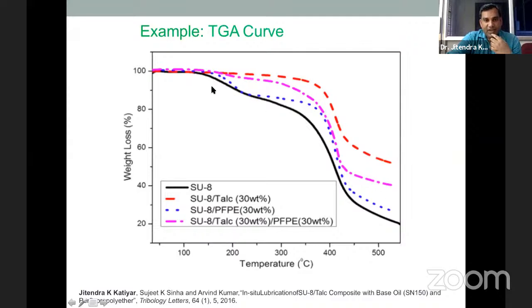Why does this start at approximately 160 or 180? In the bluish color, it is because of the liquid droplets. We added perfluoropolyether in SU8, so this decrement is because of the liquid. The liquid molecules evaporate in that range, 150 to approximately 240 or 250. Up to this temperature, the PFPE molecules are totally evaporated, and the loss in the sample is because of this.